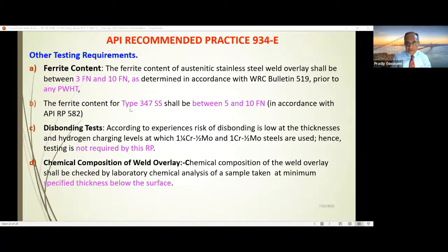And if SS 347 is used as an overlay, then it has to be restricted between 5 to 10 FN. And disbonding test, yes, since these vessels operate in hydrogen service, asking for the disbonding test seems to be logical, but what happens is that this RP doesn't recommend disbonding tests to be done for the equipment which is fabricated following these guidelines. Rather, disbonding test is asked for the vessels which operate on a much stricter or more stringent regime, that is the hydroprocessing reactors which are fabricated as per